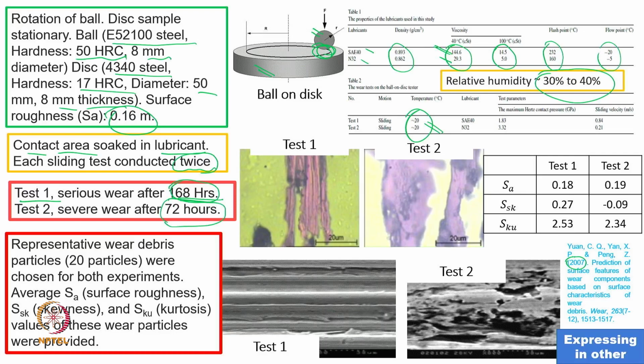Now, what is the interesting thing? In the first two cases we were observing the gear pair, or maybe say gear teeth, while these people did something like a wear debris particle analysis. They collected around 20 particles in each case, and they figured out the average surface roughness, the skewness, and the kurtosis value of those particles. So, here they are not judging the surface, they are judging the particles which have come out of the surface, after the surface has been damaged.